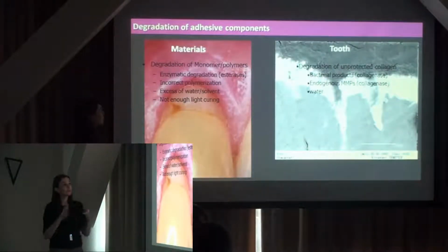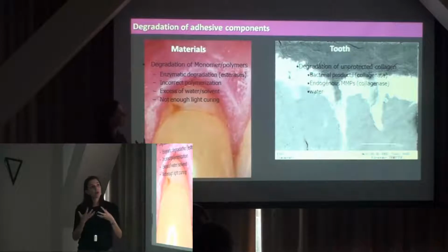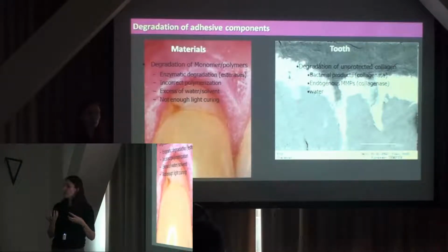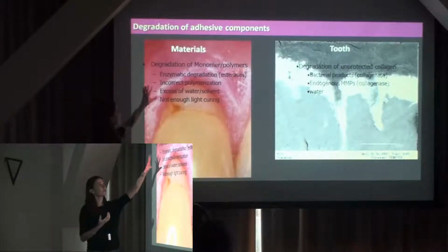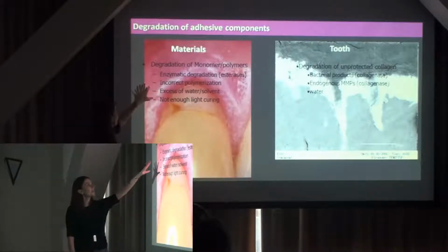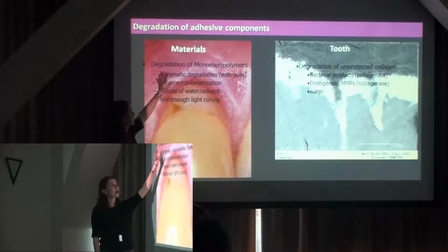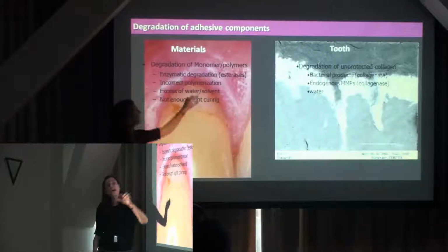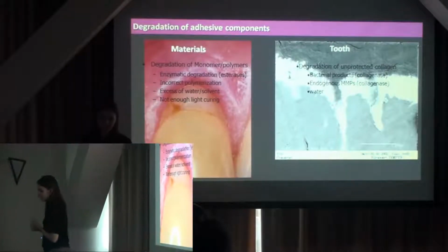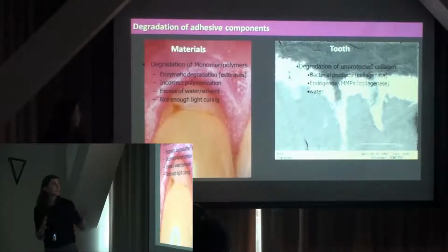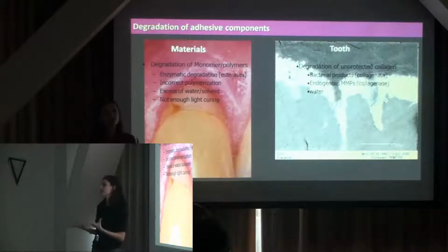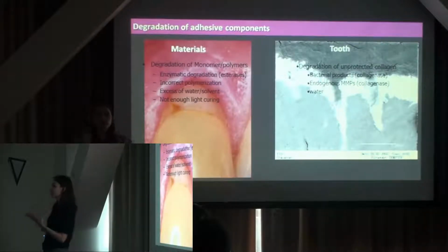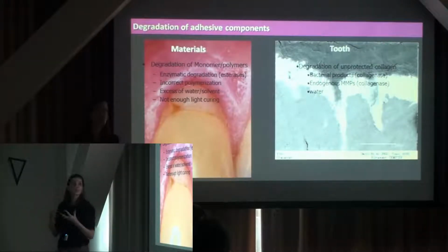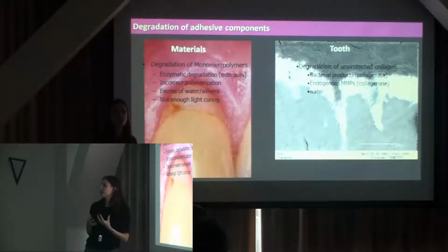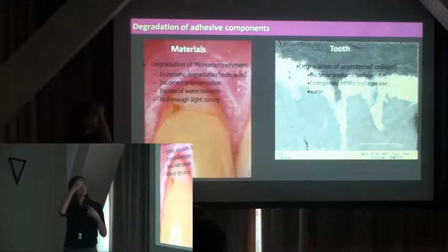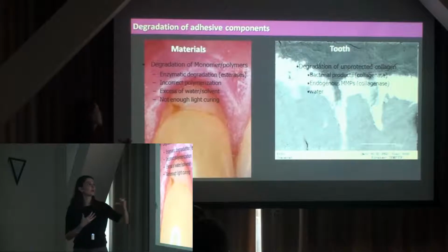So the degradation processes at that interface is caused by the tooth portion and also the material. So when we look at the material, we have some degradation of these monomers or polymers. Enzymatic degradation is a big villain here. So basically we have some esterases, some enzymes in the mouth and our saliva that in contact with these materials, so slowly will break these ester bonds and start the degradation process.